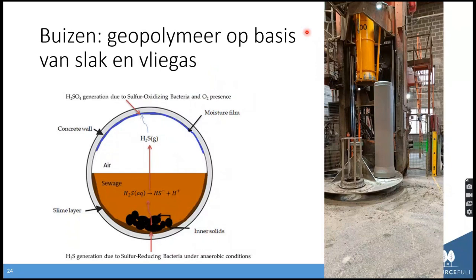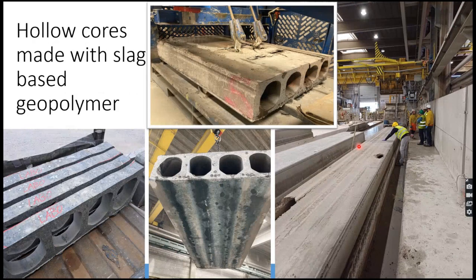Here we in fact have a double win. We get out all the Portland cement, so cube per cube we have a lower footprint, but the geopolymer is also more acid resistant against the biogenic acid attack in the sewage pipes. So we also have a double lifetime, which is we kill 2 birds with one stone, or how you say it in English. We make hollow cores.